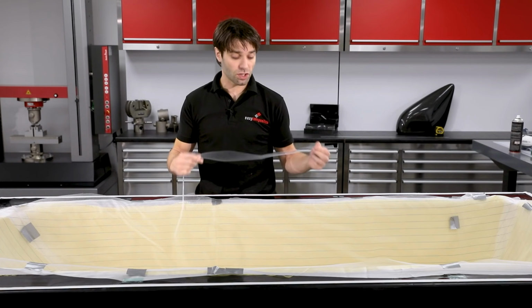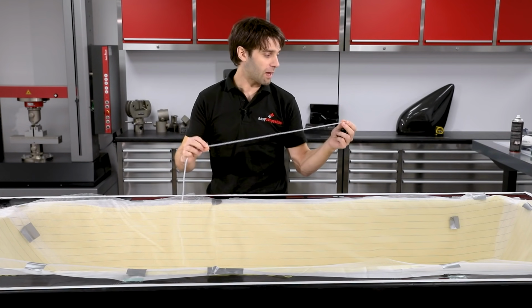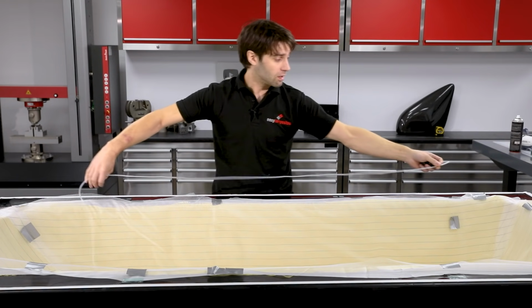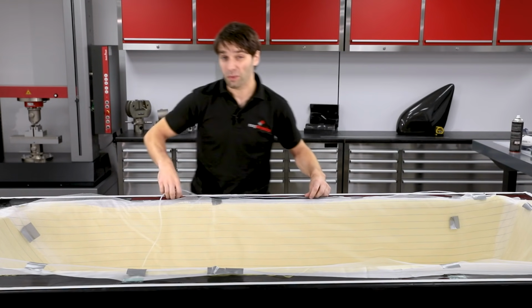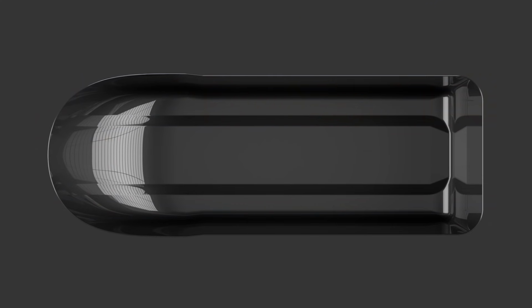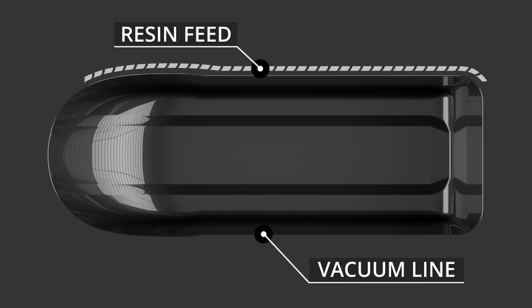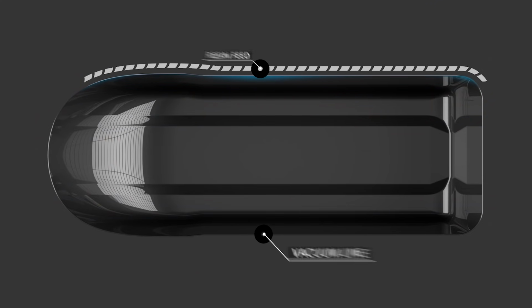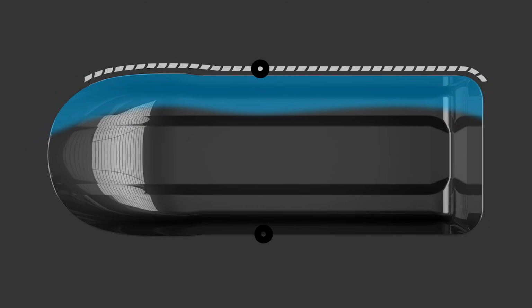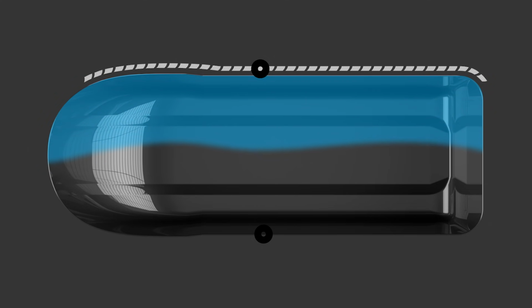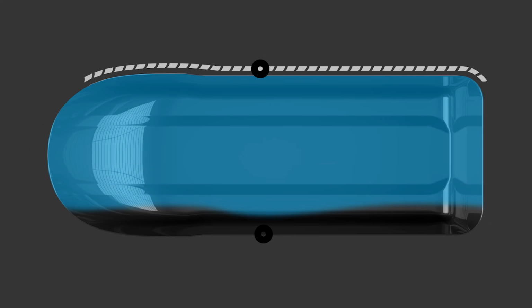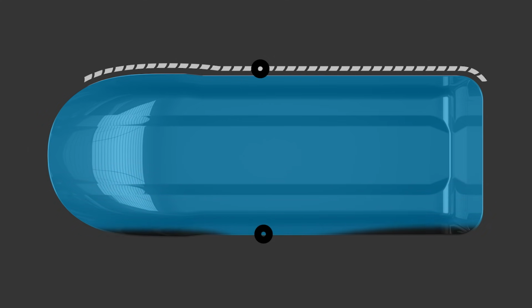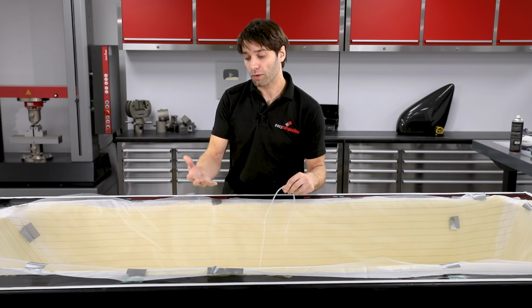The trick is reduce the distance it needs to flow from the spiral. So we could immediately reduce that by half, which would make it 4 times faster, just by running the spiral down the long side and then allowing the resin to flow across the width. So it's going half the distance, about 1.5 meters, and that'll be probably 4 times quicker. So we might be looking at something an hour and a half. So how can we improve that further?